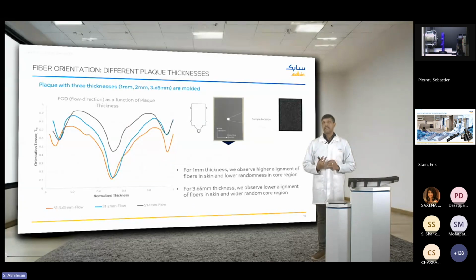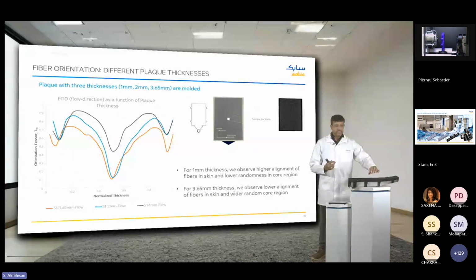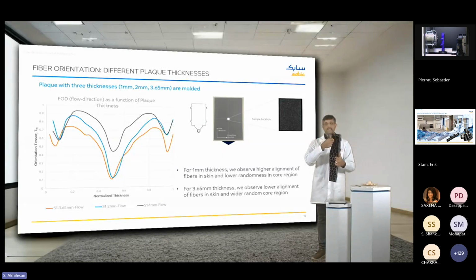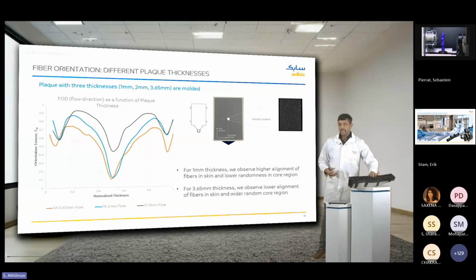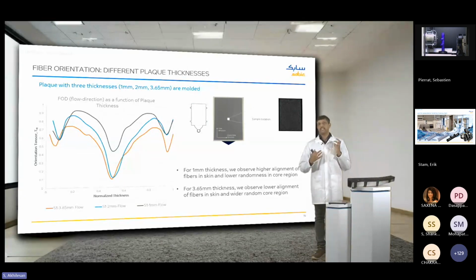The other sensitivity we consider and need to carefully model is the effect of thickness. In a real world part, different regions can have very different part thicknesses, from very thin sections to thicker sections, depending on the stiffness you want to establish. And in order to account for how the fiber orientation changes with thickness, we need to injection mold shear plaques of different thicknesses, study their fiber orientation, and model them as well. What you see on this page shows that in thinner sections, you can expect highly aligned fibers in the direction of flow versus thicker sections.